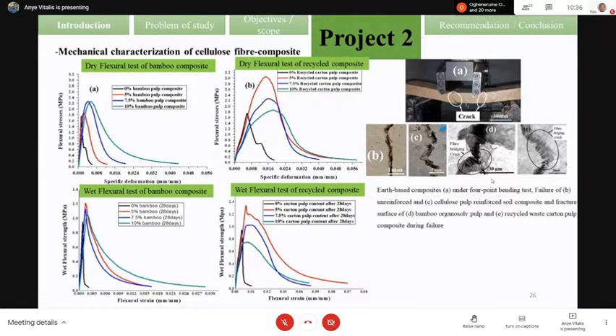Also, by comparing cellulose, virgin fiber and recycled fiber, we realized that recycled fiber had a high reinforcement efficiency compared to virgin fiber. That is consistent with the result shown in the physical property, with the dimensional stabilization of our recycled fiber. They have a good bonding between fiber and matrix compared to the virgin fiber. That is why they improve more by using recycled fiber. Also, by studying the crack tip, we realize that the predominant mode is crack tip bridging. So the fiber will behave as a crack arrestor during the crack propagation of our material.